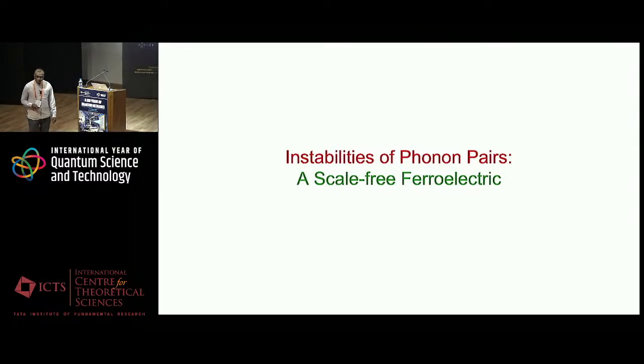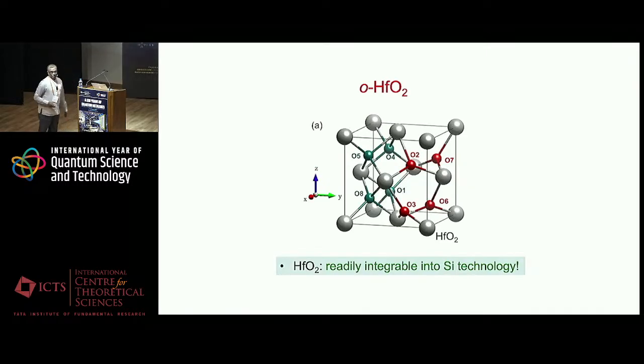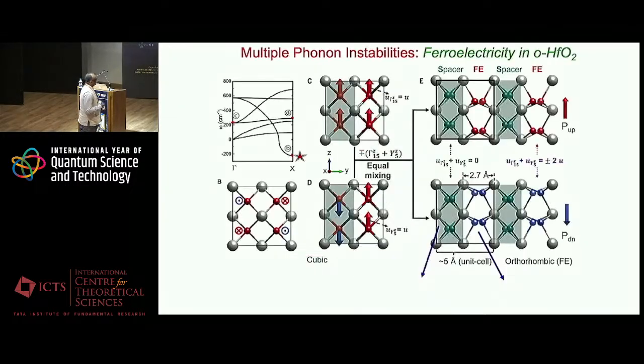Now I'm going to give you a very spectacular example of a material on which futuristic memory devices are based, and this is hafnium oxide. It's an oxide which is already used in the silicon industry, so it's very easy to incorporate in ongoing silicon-based semiconductor technology. This takes a calcium fluoride-like structure, which is shown here. Hafnium is on an FCC lattice, and oxygens are on the cubic lattice with half the lattice constant.